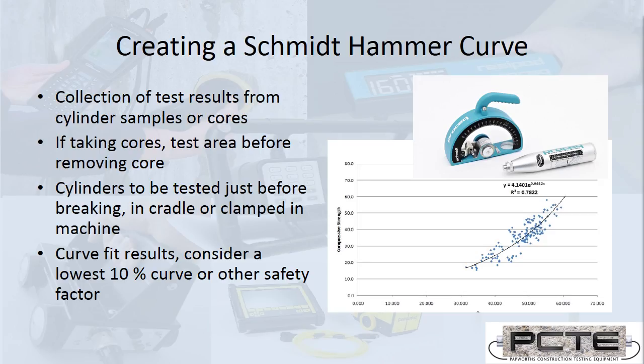So when we build a curve for a Schmidt hammer, the first step is to collect enough samples of differing strengths. If we cure 30 samples and break them all at 28 days, there may not be enough strength range. It's important that the breaks happen during the early low strength stages for an early age strength curve, and that we have enough cores or cylinders to produce a full curve. Cores are not commonly used, but if they are, it's important to test the region that the core is being taken from before it's removed, and then use that to relate to the strength of the break.